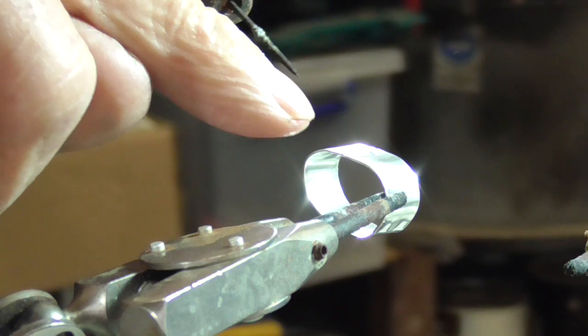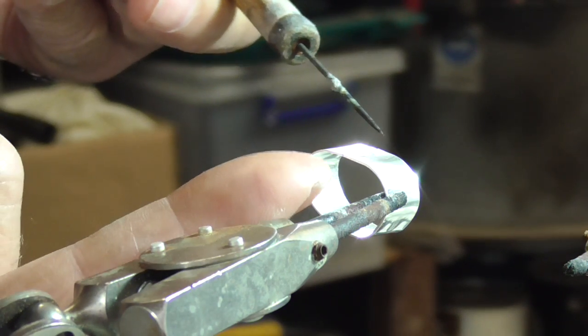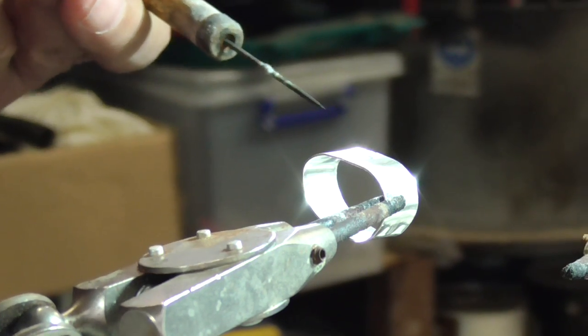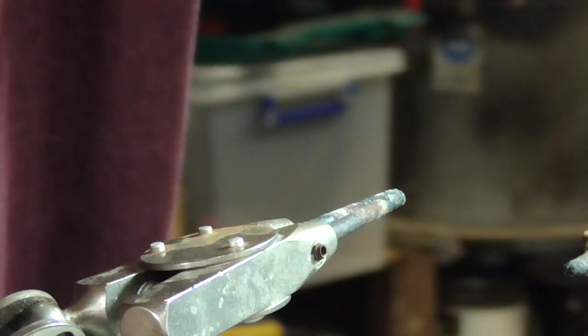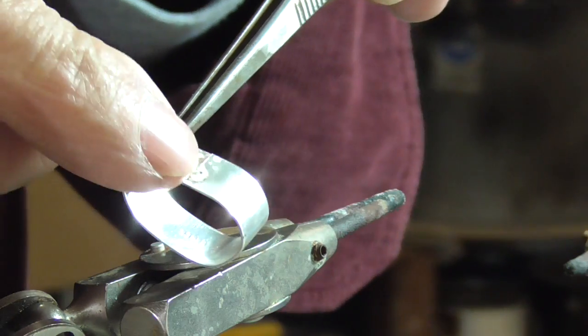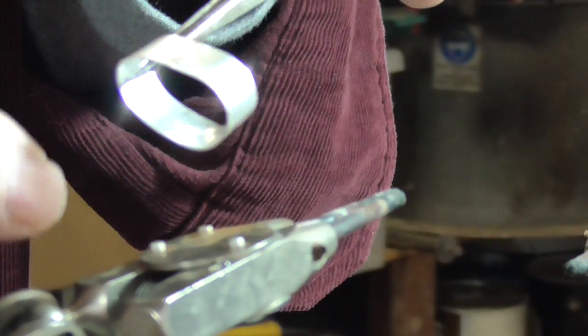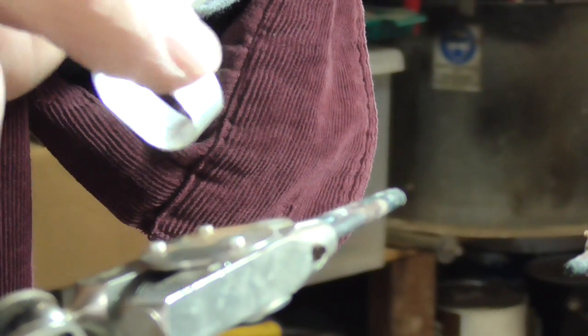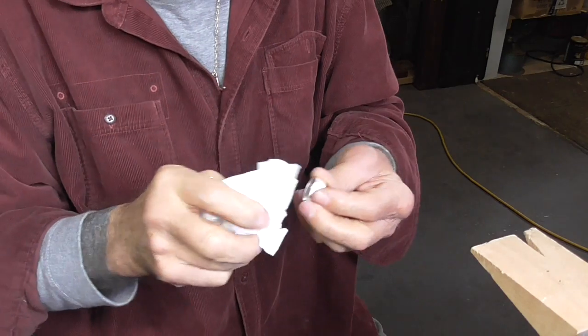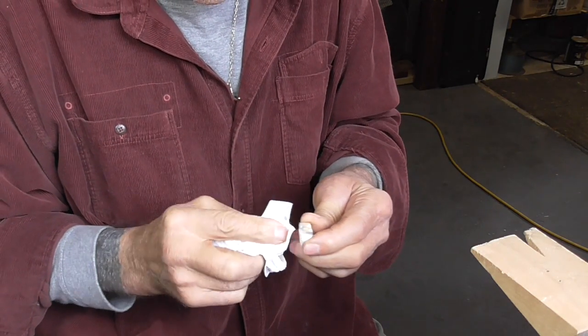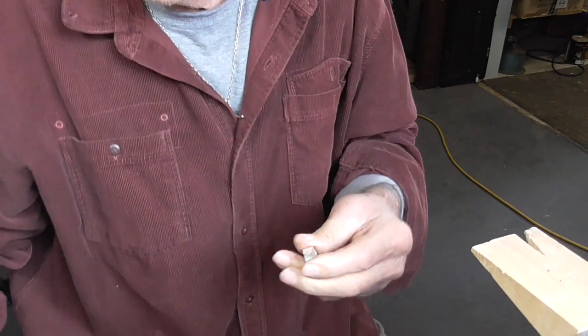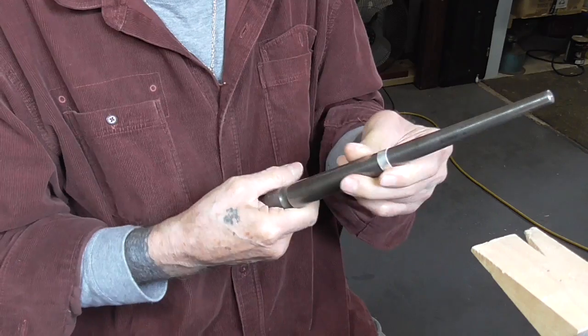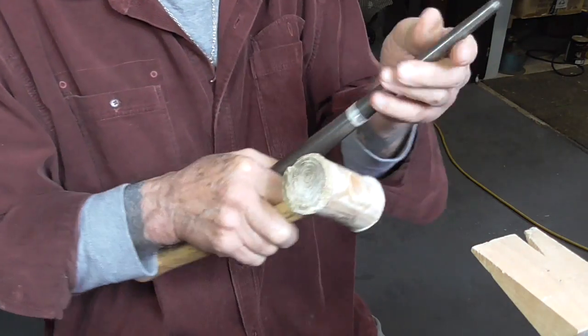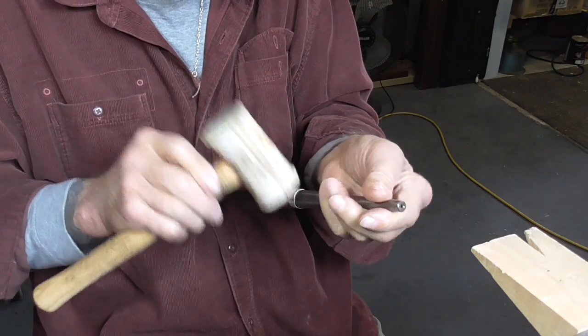Now with the solder on top and heating on the top, it'll keep most of the solder up here, and there'll just be a fine line on the inside to clean up. So quench in water, pickle now because we have to get the flux off. You can see it still hasn't oxidized, but we do need to pickle it to get the flux off, or you can just run it under the hot water tap and give that a bit of a scrub and it'll come off. So we're out of the pickle, dry the piece, check your solder and make sure it's beautiful. Hammer this up on the ring mandrel with the rawhide hammer. Be fairly gentle because this is fine silver and it's easy to stretch it.